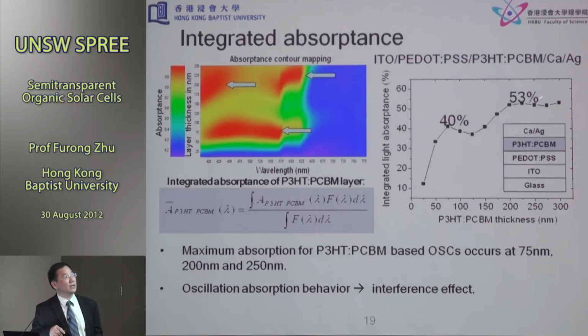So when you're looking into another relative maximum, you see that if you choose a layer thickness around 225 nanometer, then you're likely to absorb 50% of the light in these devices. So if you're looking into a bulk heterojunction single junction cell, probably this is the layer thickness you're looking at. Anywhere different from this is not going to guarantee that you will absorb the maximum of the incoming light. This is very interesting, and it is very easy to calculate. For a tandem solar cell, using the same technique, we'd look at devices corresponding to that kind of thickness.